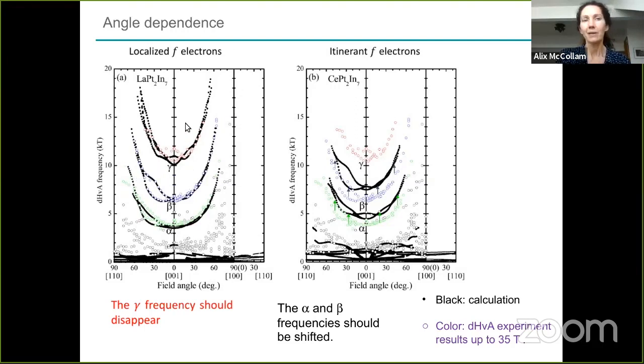Absolutely. Localized f-electrons, the calculations are in black and the data are in color. So the circles here are all experimental data of the frequency as a function of angle. And you can see that for the localized case, they agree extremely well. This is the calculation for the itinerant case. You see the gamma frequency disappears in the calculation for the itinerant case, but we have data there, so it really looks like we have a localized scenario. The alpha and beta frequencies agree extremely well with the localized case.